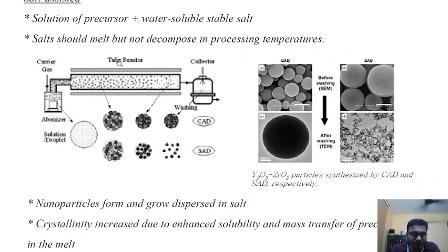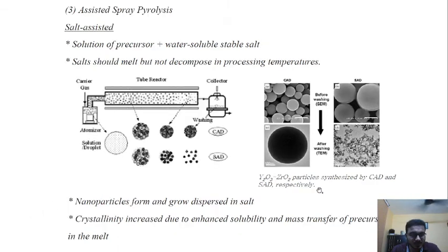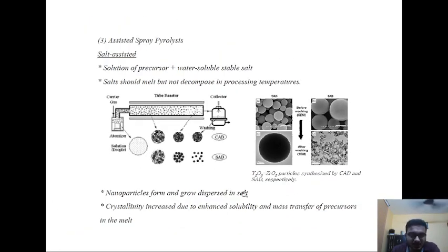It passes through the tube reactor, and there is a collector along with the washing. This figure shows Y2O3 and ZrO2 particles synthesized by CAD and SAD respectively. Here nanoparticles form and grow dispersed in salt, and crystallinity increased due to the enhanced solubility and mass transfer of precursor in the melt.